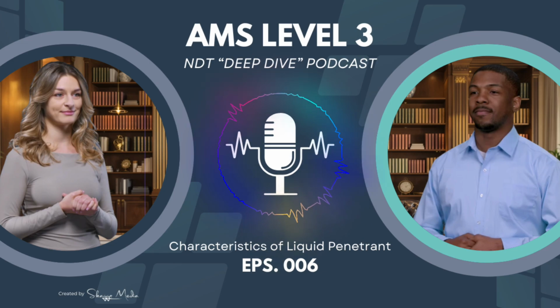It is. But, and this is crucial, this only works if the liquid wets the surface. If that contact angle is too high, say 90 degrees or more, then there's no wetting. And no penetration. The whole process stops before it starts. Okay, so the liquid gets pulled in by this capillary action. But then how fast does it move?